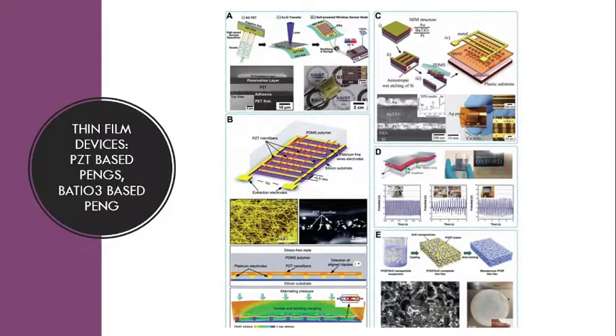Moreover, a bio-inspired flexible PENG based on barium titanate was presented in 2013, as seen on the right panel. In this work, anisotropic barium titanate nanocrystals were deposited on a viral template via self-assembly of metal ion precursors. The filamentous virus provided a template for the deposition of anisotropic, entangled, highly crystalline barium titanate nanostructures. This flexible nanogenerator based on a virus-enabled piezoelectric structure can generate electricity of about 6 volts and 300 nanoamperes without additional structural stabilizers, indicating the high output is related to the important structure at the nanoscale. So this method of using a biotemplate is facile and has particularly enlightening meaning for flexible PENG design and applications.